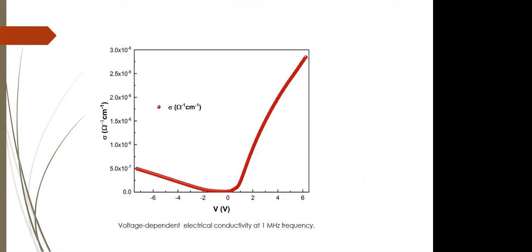This graph shows us the variation of conductivity at the 1 megahertz frequency according to the voltage. If we look at the graph, it's seen that the conductivity values of the sample are small in the inversion region at applied reverse voltage. It's seen that the conductivity increases rapidly when it passes into the depletion and accumulation regions at the forward bias voltage.